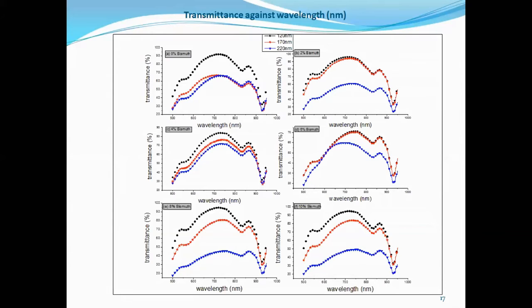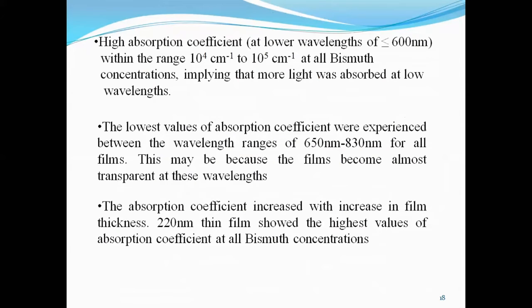At the same time, you can see the thinnest film of the 3, the 120, is always giving the highest transmittance. So this clearly indicates that transmittance increases with the decrease in film thickness. There was also a high absorption coefficient for all the films at all bismuth concentration. They recorded a high absorption coefficient of 10 to the power 4 to 10 to the power 5 for all. I've not displayed that graph here, but the lowest values of absorption coefficient were between the wavelengths 650 to 830 generally for all the films.